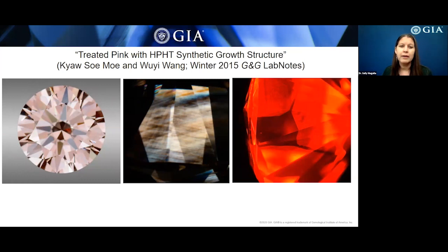So this fancy pink type 2A diamond showed spectral characteristics indicating the multi-step treatment of HPHT processing, irradiation, and annealing. Tatami and banded strains with strong interference colors could be seen under cross-polarized light, which you can see in the center image, and this is something that is consistent with naturally grown diamond.